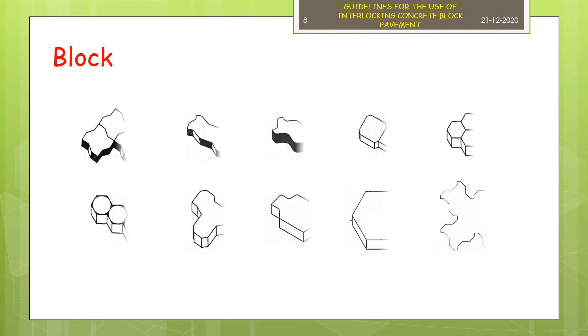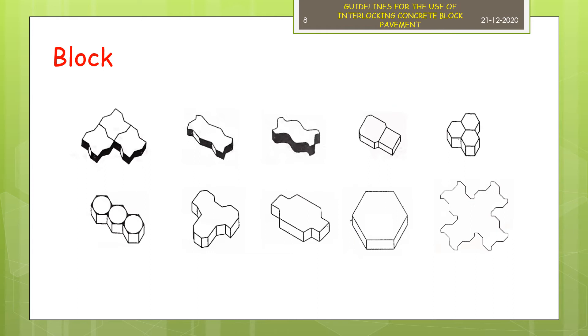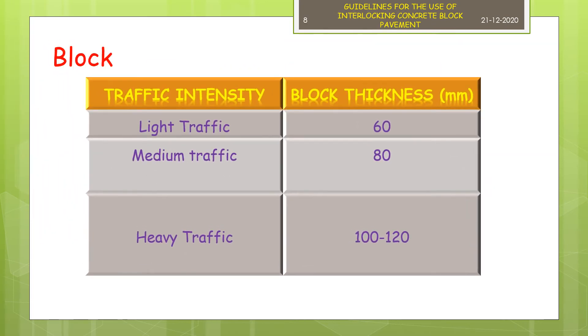Interlocking concrete blocks come in different thicknesses. These blocks serve as a wearing surface but at the same time help in reducing the stresses imposed on the subgrade and also help in resisting pavement deformation and elastic deflections, similar to the base course of a flexible pavement. A block thickness of 60 mm is sufficient for light traffic such as pedestrian, motor car, bicycle, etc. For medium traffic a thickness of 80 mm is commonly used. For heavy traffic roads, block thickness of 100 to 120 mm is used.